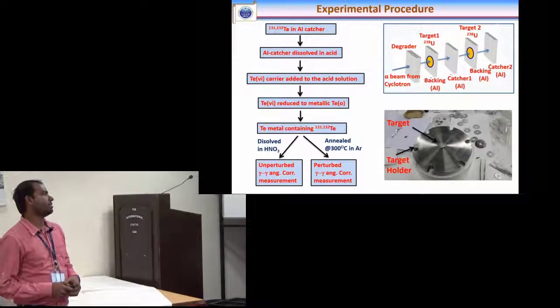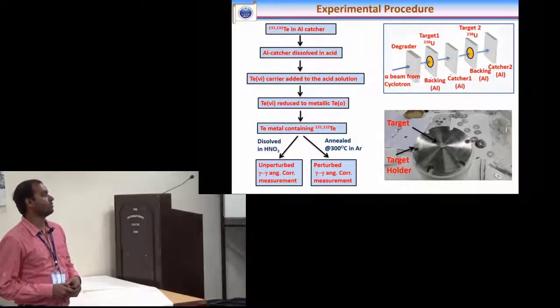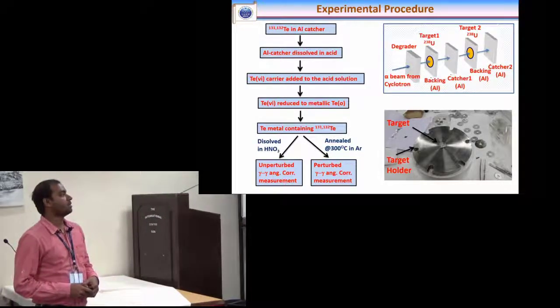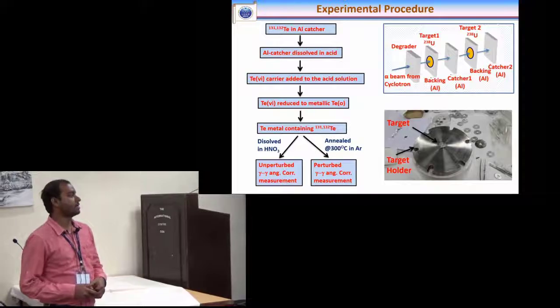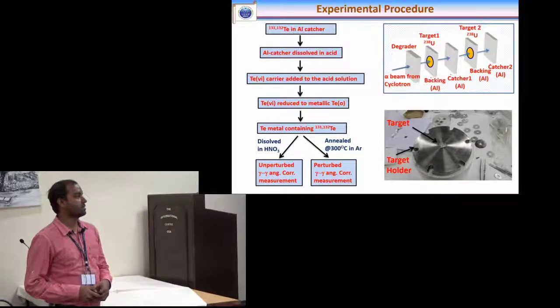Al catcher was dissolved in acid medium then we have added the tellurium carriers and then finally we have reduced the tellurium metal matrix and then annealed at 300 degree centigrade.